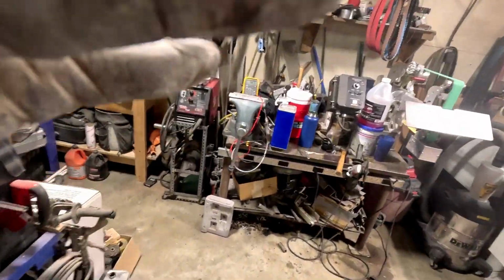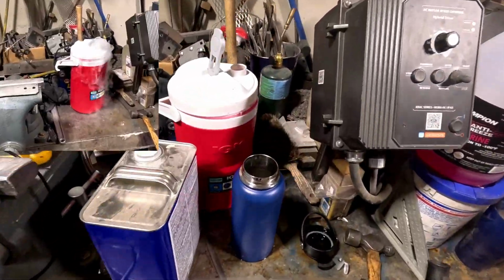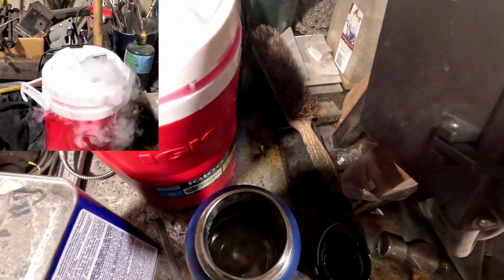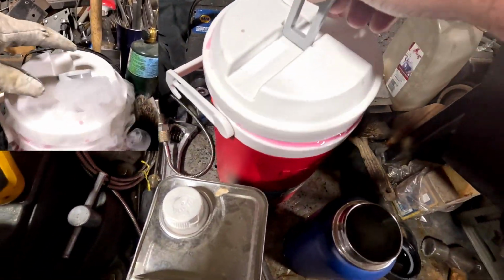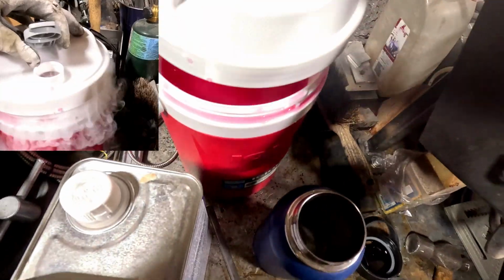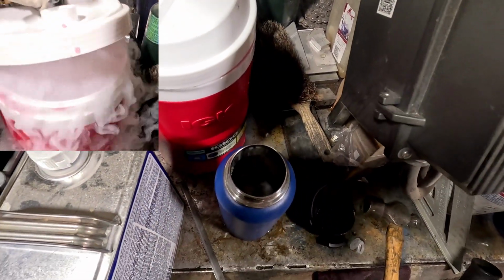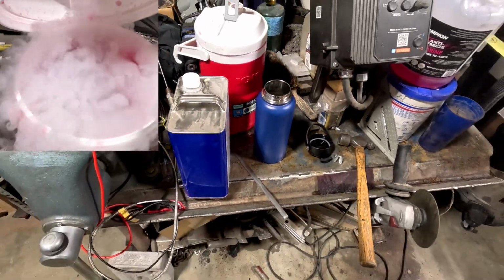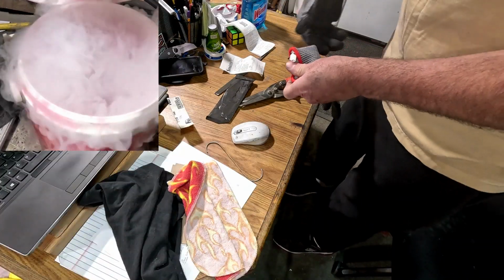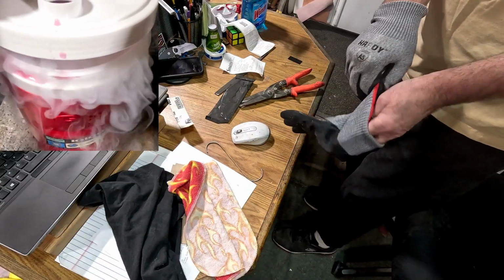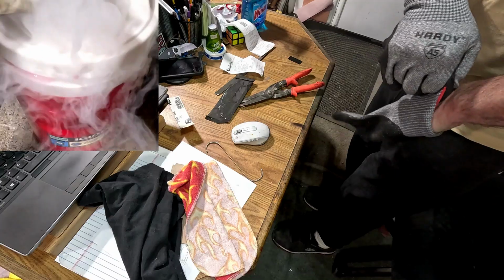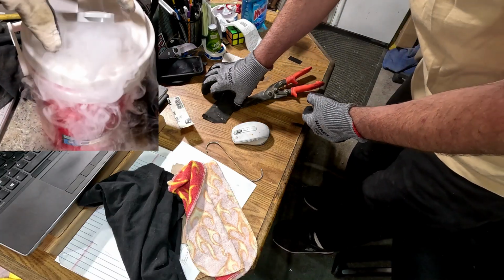Let's check out the cryo setup for the next step. We tried to use RV antifreeze and dry ice to make the negative 100-degree bath needed for cryo treatment, but it did not turn out like we wanted. That slurry only got down to about negative 10 degrees. The antifreeze formed a frozen shell around the dry ice and insulated it from cooling down all of the liquid.